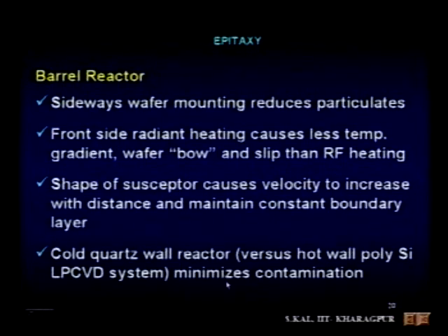Cold wall reactor versus hot wall polysilicon LPCVD system minimizes contamination, because in a barrel reactor we are using a cold wall reactor; radiant heating from the sides will heat the susceptor but not the wall. Walls are cooled using cold water circulation. So the cold wall reactor minimizes contamination. Okay. These are the advantages of barrel reactor compared to other configurations, and that's why they are popular.